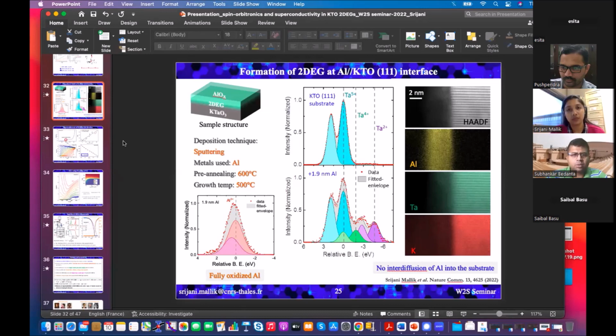But I just wonder, let's say you did not have oxygen deficiency. Each slide, whenever you talked about the 2DEG nature, you explained it. So is there a way to confirm that it's a 2DEG, or do you really need XPS to show that there is this oxygen deficiency as a function of aluminium thickness? There can be many origins of achieving the 2DEG, but in my case, I am always getting the 2DEG due to the oxygen vacancies. So if there is no oxygen vacancy in my sample, there is no 2DEG.